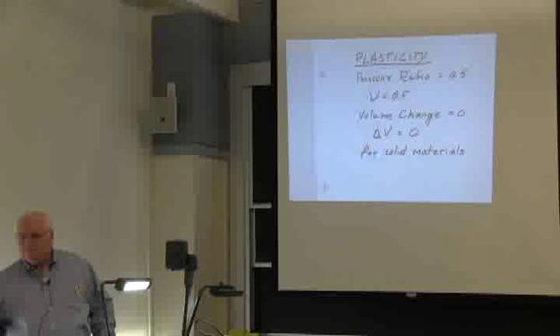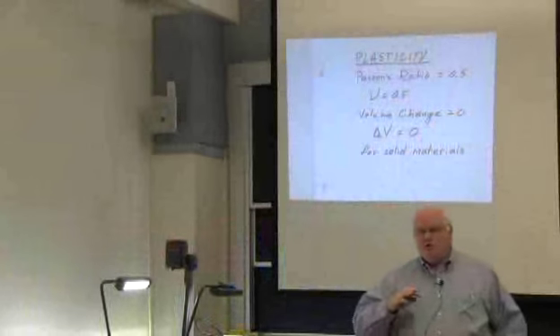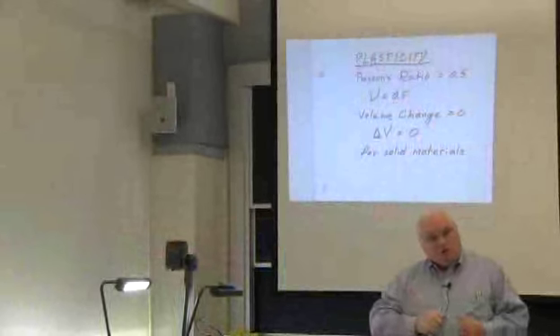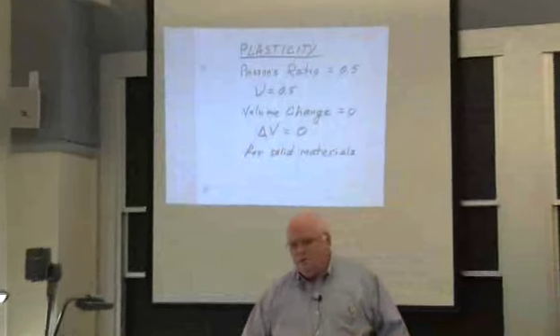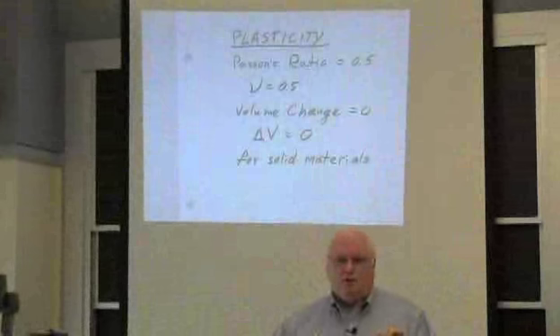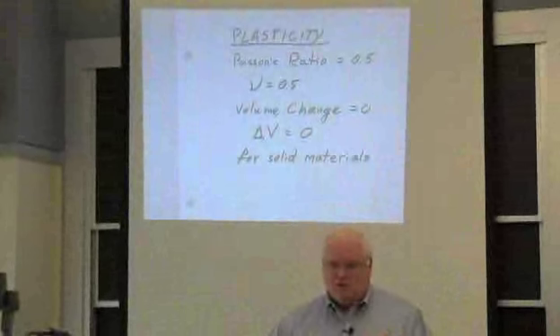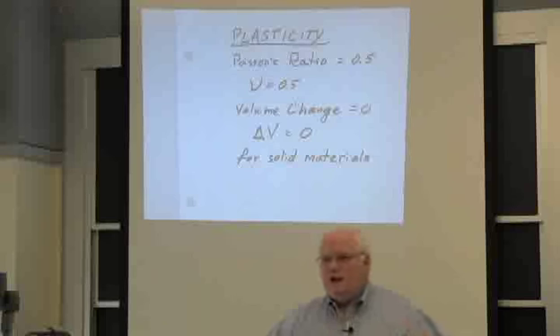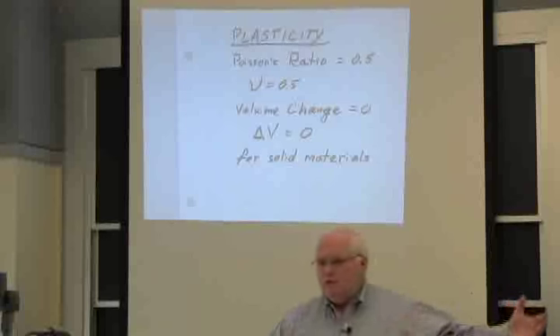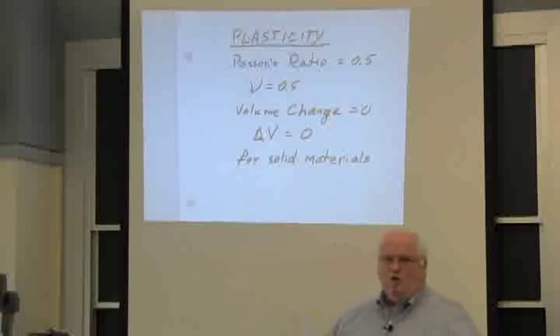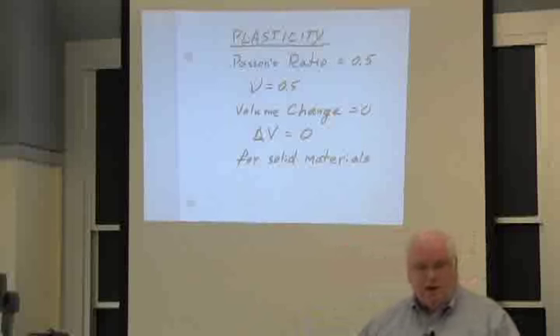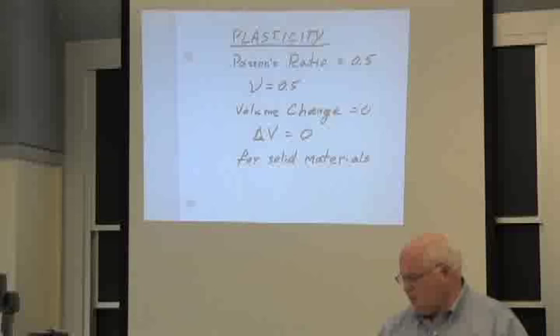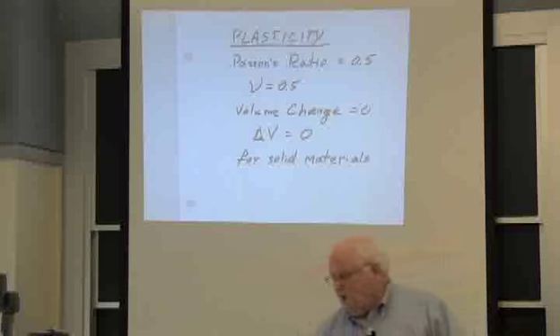In plasticity, which I'm going to be dealing with for the rest of the term, we don't usually worry about the elastic behavior. We're worried about deforming the thing. And the elastic behavior typically lasts out to about 0.2% strain. Well, 0.2% strain is not very much. We're interested in 10, 20, 30, 40% strain, maybe even more. So who cares about the elastic component, which is only 0.2%? We can usually ignore the elastic component in deformation processing. You can't when you get to fracture and fatigue and things like that, because you're at lower strains. So far as that goes.